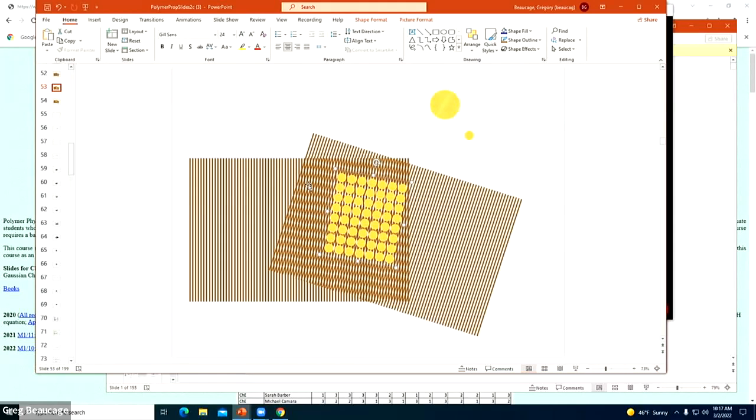Those bands are split into different energy levels. One is if it falls back to the same energy level, and the other is if it falls to a different energy level. So alpha and beta are the two dominant wavelengths. The alpha is 1.54 and beta is like 1.39, I think. You want to get rid of the beta, so you put in nickel; it absorbs it. It's got an absorption band that takes care of that. Anyway, that's the cheapest X-ray camera.